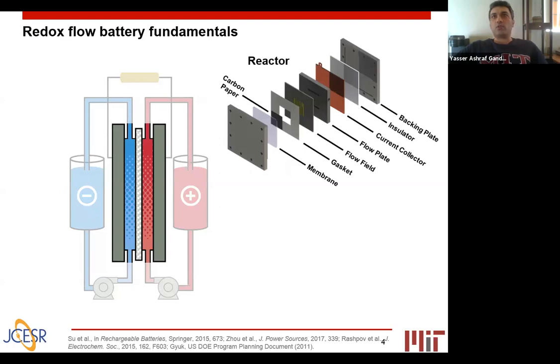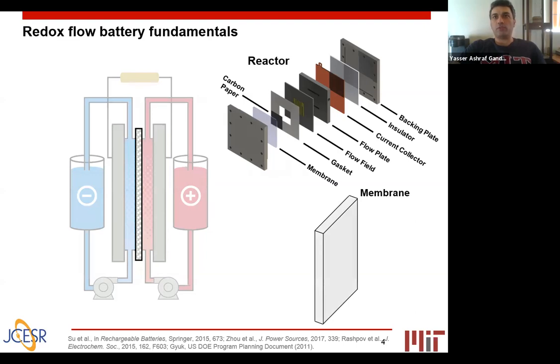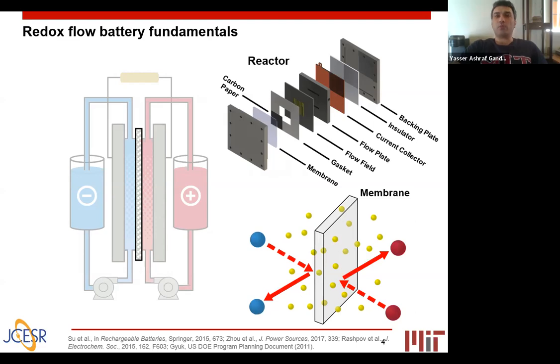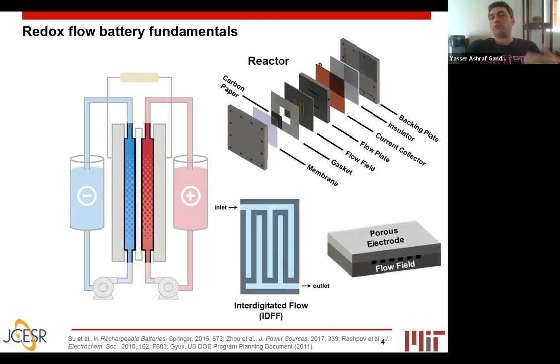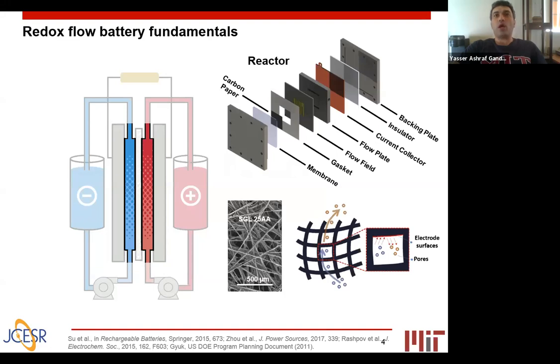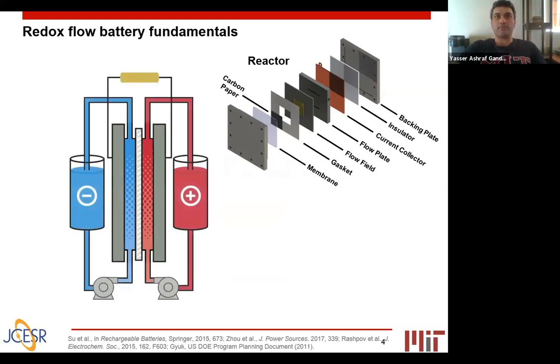The reactors include different components: flow plates, flow fields, membranes, and the electrodes are some of the major components. Membranes, as the heart of the reactor, must provide an ionic pathway for shuttling ions. Shuttling ions are responsible for maintaining charge neutrality throughout the reactor. And they must also prevent crossover of electroactive species, because otherwise, as a result of crossover, we might have reversible or irreversible capacity decay. Flow plates can have different designs and are responsible for distributing electrolytes across the electrodes. And we usually use high surface area porous electrodes for providing active area for the reactions to take place.